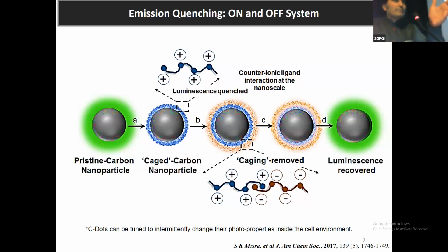Now that is the limit where one needs to push it forward, because we know that for our biological tissue, our blood, the maximum absorption of light is in that range of 500 to 600. So you want to push it beyond. For that you have to incorporate or passivate different kinds of molecules, polymers, dye molecules, pigments, so that it can be shifted toward near IR, and then it becomes a very magical bioimaging agent, which can also be used for 2-photon imaging, deep tissue penetration and imaging.